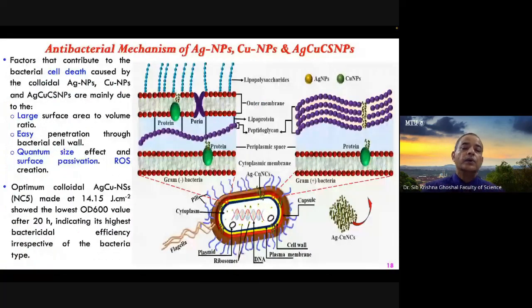And here we directly apply these nanoparticles, the optimum core-shell structure, on E. coli bacteria. We have also applied them to three other bacteria recently. And we have found that these nanoparticles can easily penetrate, because the size of the nanoparticles is much smaller than the membrane perforations in the bacterial cell.